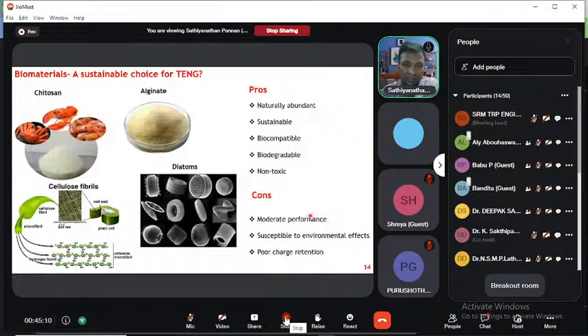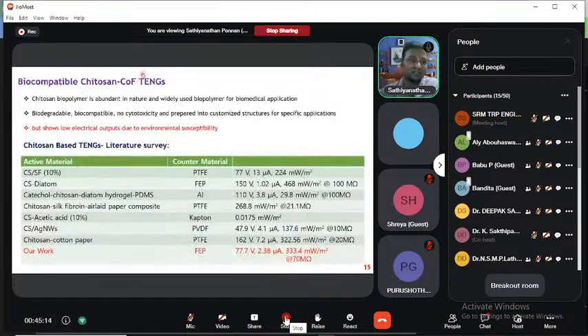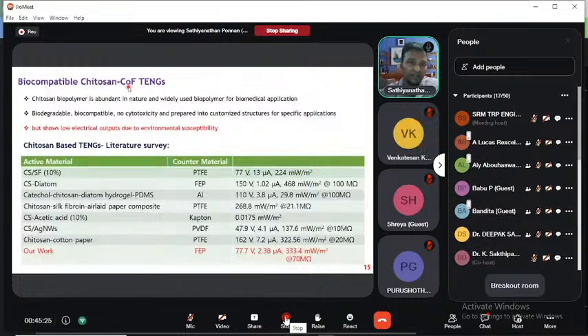So how can I solve this? For this, I want to make a composite. I chose a covalent organic framework as a filler material, because it is also biodegradable and biocompatible. I designed this material to be biocompatible and biodegradable, showing no cytotoxicity. So I incorporated it into the biopolymer chitosan and fabricated this device. Here I just want to show the literature: these are the publications based on chitosan composite systems. We published our work, in which we reported the highest power density, about 333.4 milliwatt per meter square, the highest compared with published work so far.